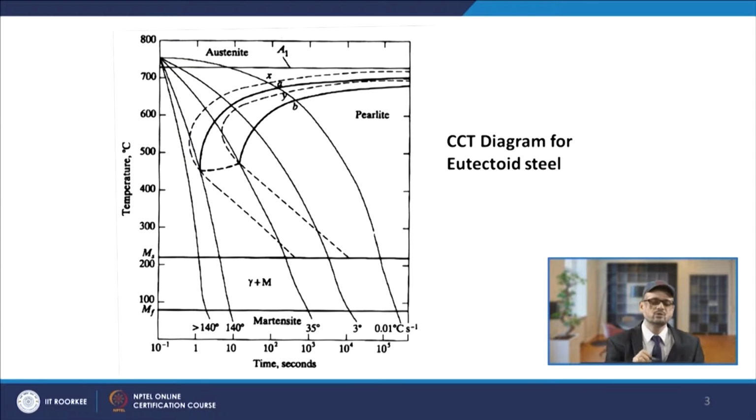So, that basically defines the concept of the critical cooling rate. This is the critical cooling rate because it is just touching the nose of the C curve outer part. For the full hardening of the steel, for the full martensitic structure, your cooling rate must exceed this value. If it is 140 or more than 140, you get the full hardening, the full transformation from austenite to martensite.